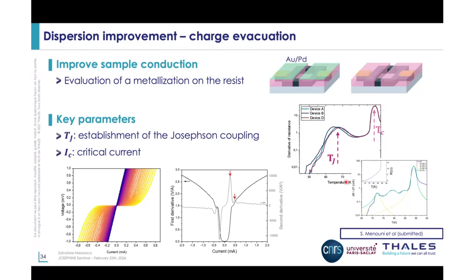And you can see that for this specific sample, we were lucky enough because it showed some kind of uniformity and some kind of homogeneity because we had only one peak. But for example, for this one, homogeneity was not there at all because we had 3 different TJs, meaning that from the 8 junctions that we had in series, we had at least 3 sets of different TJs, so a pretty high inhomogeneity. The same was done for the critical current, where we measured the IV curves, and we defined the critical current as the peaks of the second derivative, so the gray curve here. And you can see that in the specific case, we had 2 values of critical currents, again, highlighting inhomogeneous junctions.